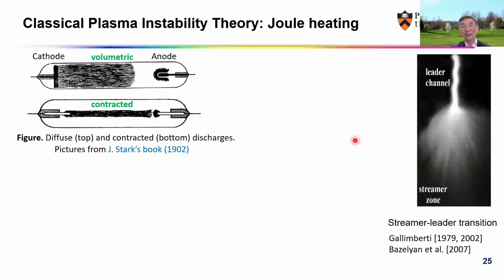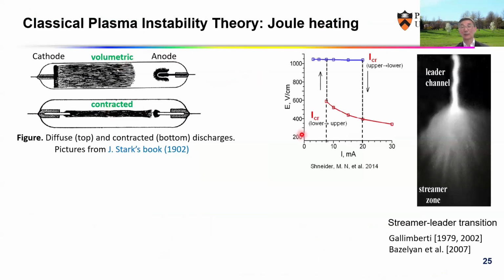With that question, I tried to look at what the instability of plasma is. Plasma sometimes is volumetric, sometimes contracted. It's because of thermal instability, just like in combustion. With the electric field, if you put in a very small current, the electric field is high and the plasma is uniform. If you increase the current, the plasma gets hot and contracts. This you call ignition, as in combustion. If you reduce the current, it comes back, and that is extinction. So this is very typical, becoming like an S curve in combustion.